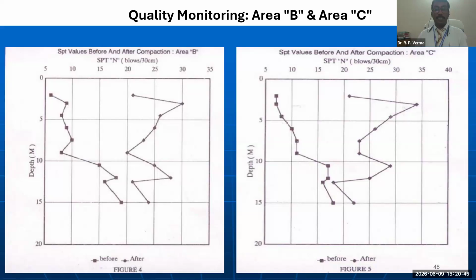A dramatic shift of the SPT curve to the right, even at depths of 5 to 10 meters, where loose sand previously threatened a structural collapse under seismic load. The refined soil skeleton now shows high N values, well above the minimum safety threshold.